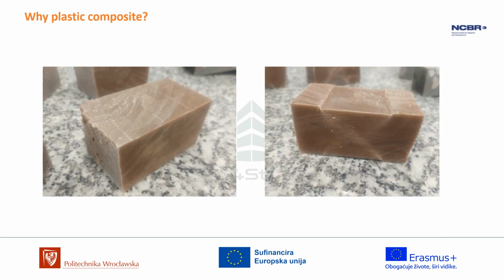The manufacturing process involves compounding shredded plastic with fine brick aggregate at elevated temperatures. The polymer melts and coats the ceramic particles, acting as a continuous binding matrix. The temperature is not so high that it affects the waste brick aggregate at all. Once extruded or compression molded into shape, the composite cools into a tough, water-resistant solid block.